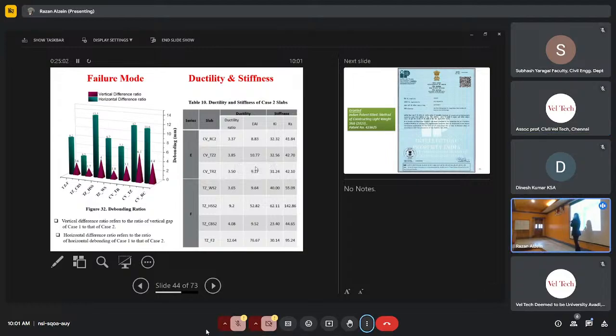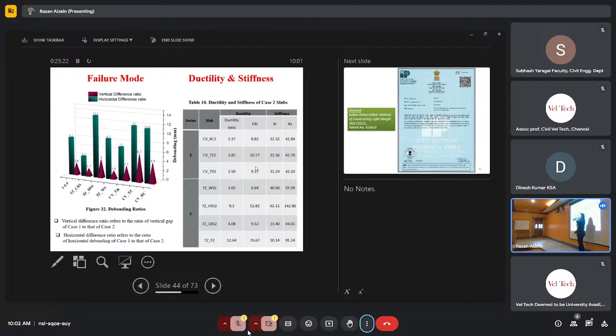Moving into the failure mode, for comparing the failure mode I have come up with two concepts. The first one is the vertical difference ratio, the second one is the horizontal difference ratio. The vertical difference ratio refers to the ratio of vertical gap of case 1 to case 2, and the same thing is applicable for horizontal difference. We can see that in all the cases there is a huge improvement in case 2 slabs. Moving into the ductility and stiffness of case 2 slabs, we can happily say that the ductility was much better, but the stiffness wasn't.